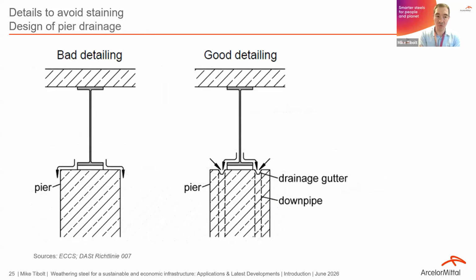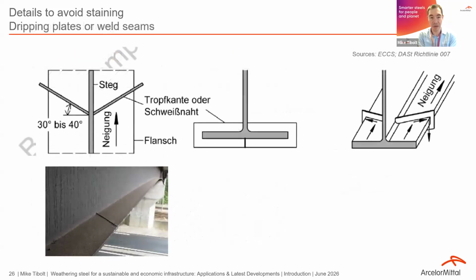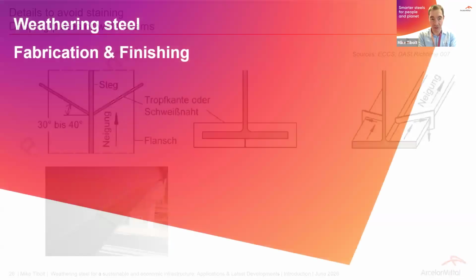The same holds true also for the pier. At the piers, you should also apply a drainage system, so that the water can be evacuated properly without getting into contact with the pier surface itself. At the end of the bridges, it is advisable to use dripping plates or weld seams, so that the water that normally would get into contact with the abutment wall will drip off before, by having a weld seam, as you can see in the picture below, or by welding some plates at the end of the lower flanges to evacuate the water.